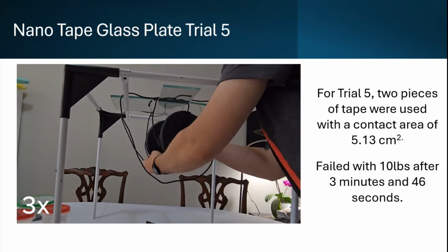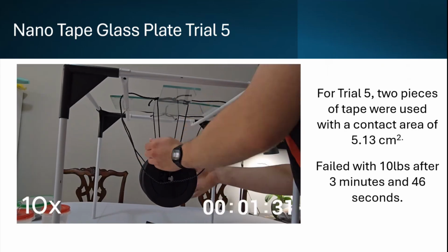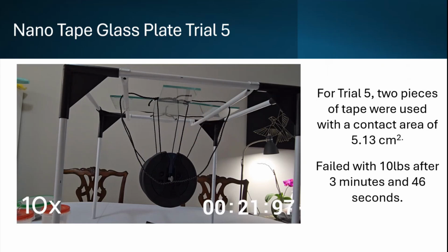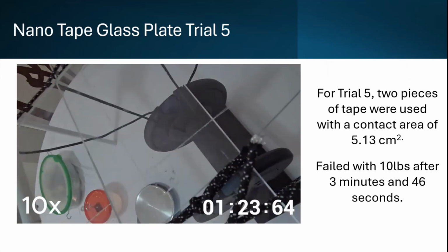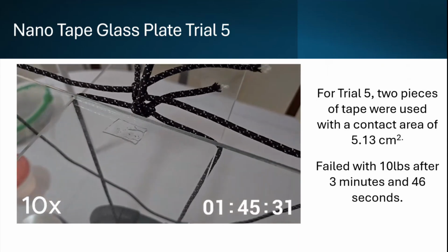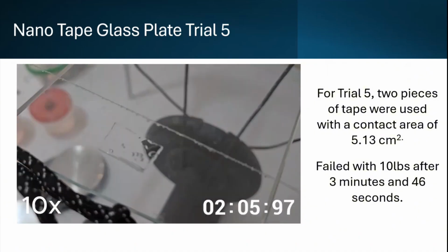Trial 5, 2 pieces of tape were used with a contact area of 5.13 centimeters squared. This is a little bit less than trial 4. This failed after 3 minutes with 10 pounds. So it lasted for much, much longer than the other trial.